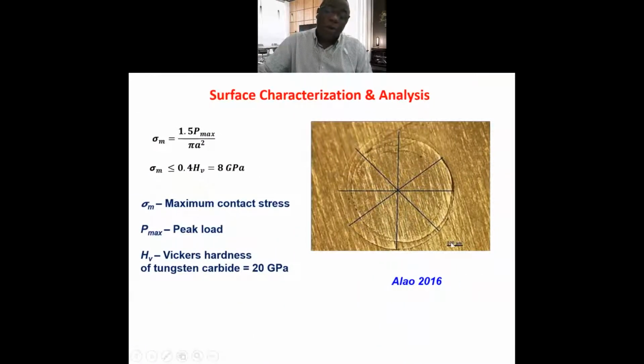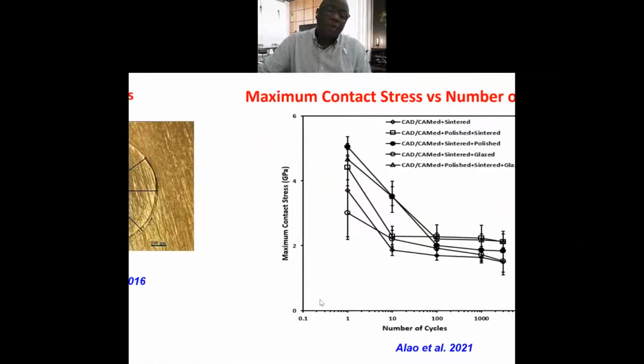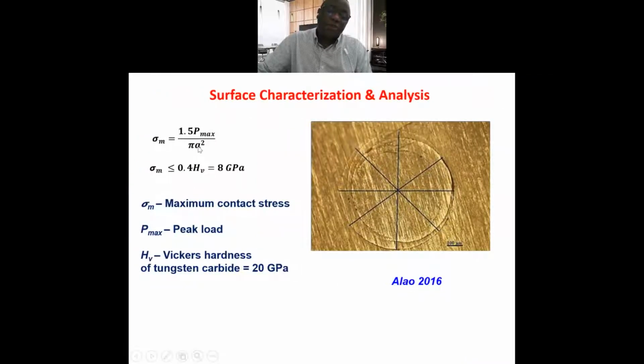So this is how we formed the contact. The maximum contact stress is governed by this equation. So the contact radius is formed this way. After the experiment, we took the optical microscope picture, then we draw about 4 lines, find the length of the line and divide by how many. So we have 1, 2, 3, 4, so we have about 8 radii there. So we divide by 8 in order to get A.